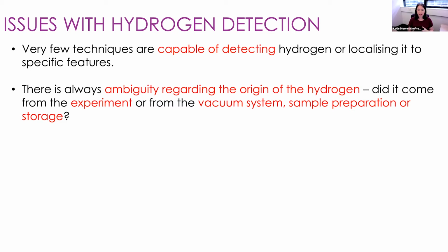Furthermore, when we're thinking about NanoSIMS experiments in this area, there's always ambiguity regarding the origin of the hydrogen. So did the hydrogen that you're detecting in the NanoSIMS come from your experiment where you deliberately introduced hydrogen into your metal through a charging experiment, for example? Or could it have come from the vacuum system? Although we're looking at very, very low vacuum levels in the NanoSIMS, there is still residual hydrogen in the NanoSIMS. It's very difficult to pump that out. Could it have come from sample preparation as we're polishing and grinding our samples in water, or just simply from storage by having water vapor in the air, for example?